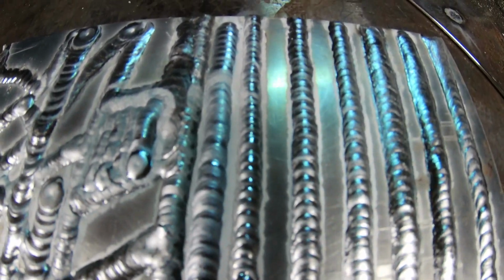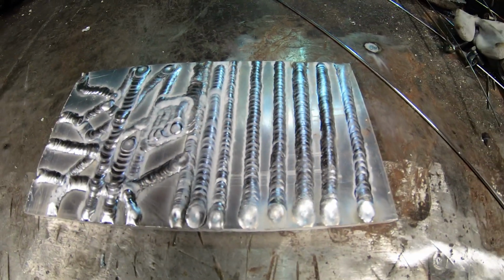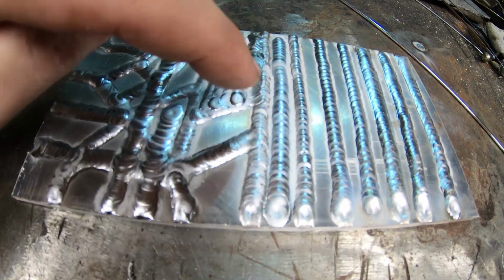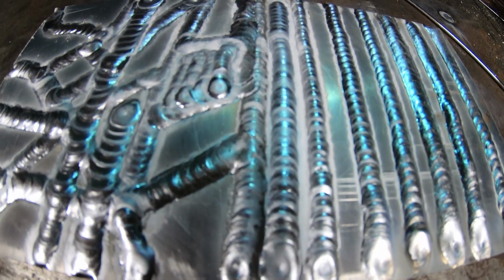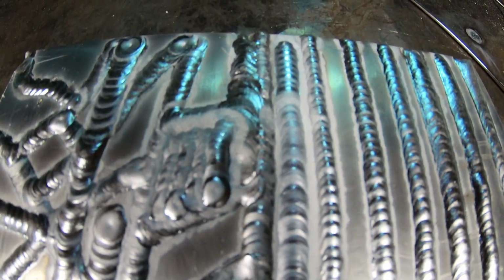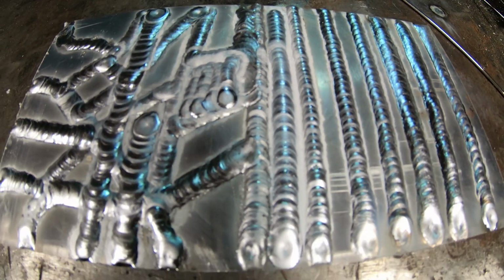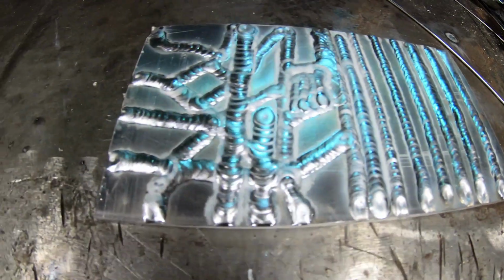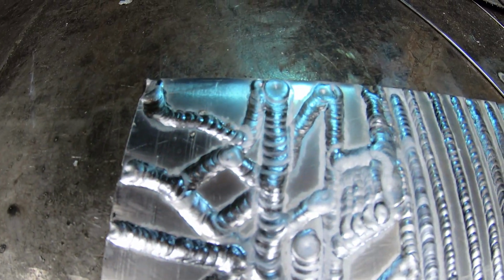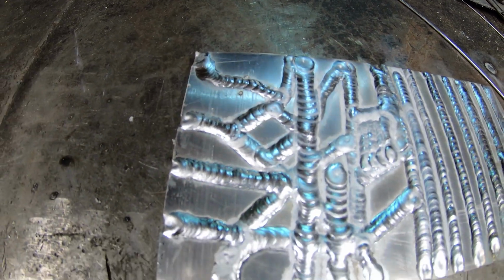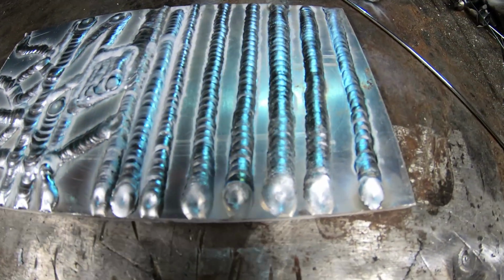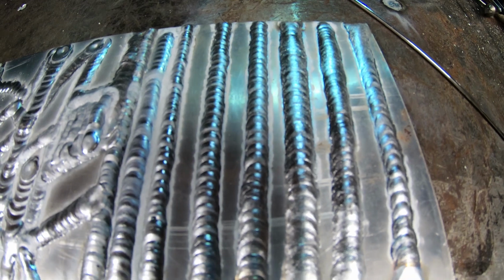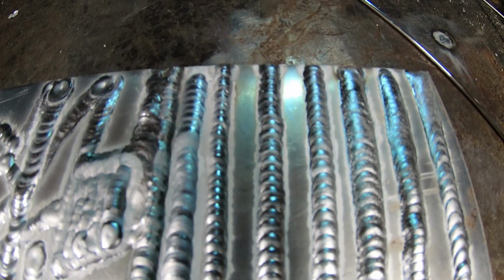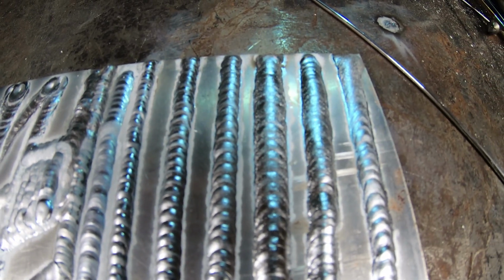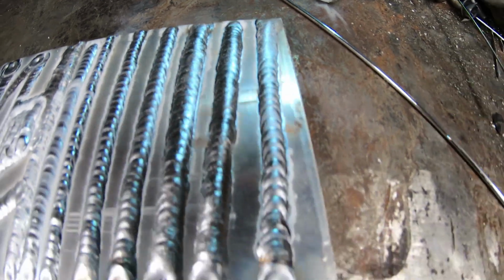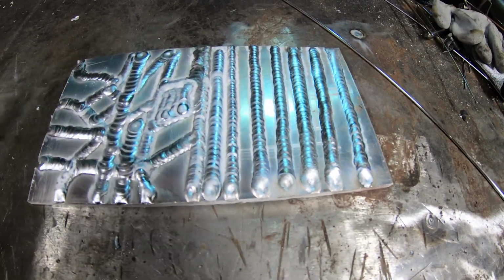So what you'll get is some real weirdness. But you can see that middle bead right there is one that we did with pulse, and that came out pretty good. That was at, I think, 5 pulses per second. So that one actually looks really nice. The rest of these came out really nice too. And again, because I didn't let any of this cool, the beads are a little funky. As the plate got hotter, the beads start to spread out a little bit, and as the plate heated up, it got nastier and nastier.